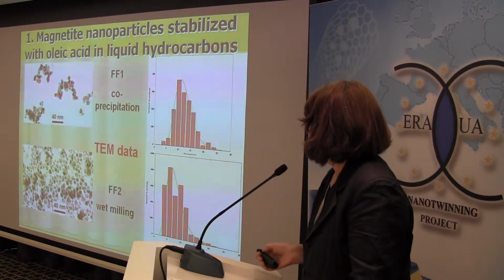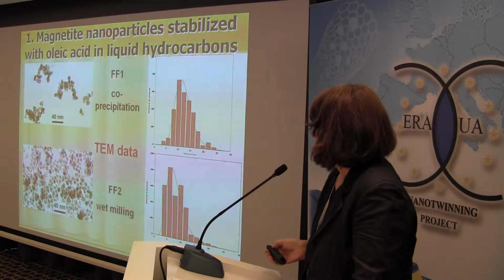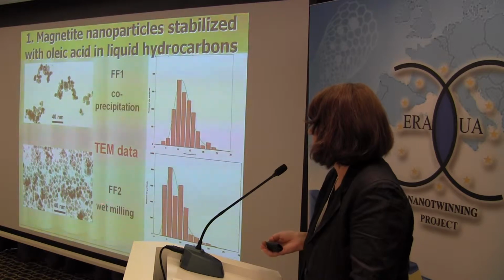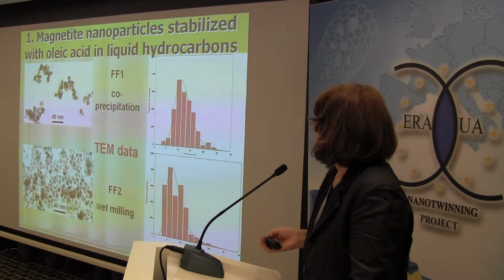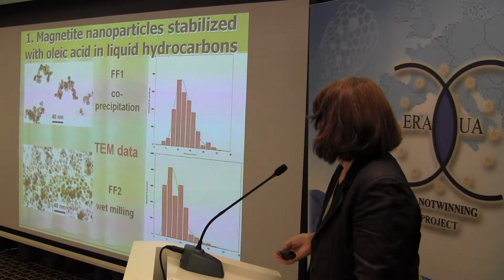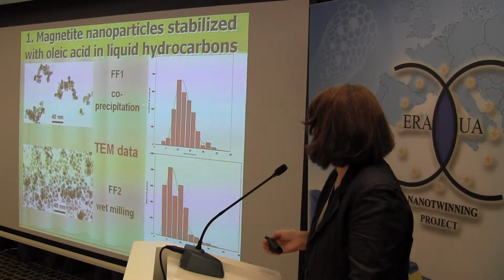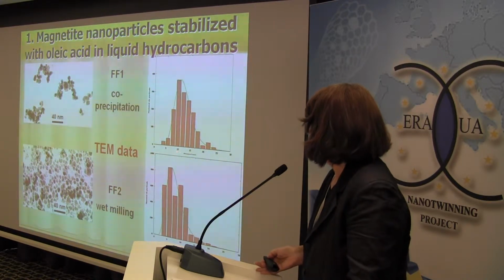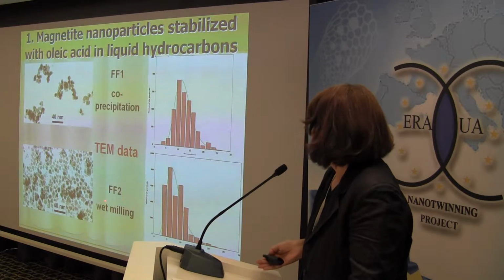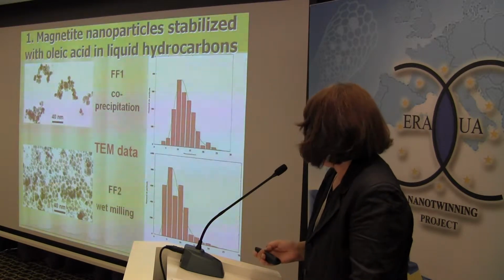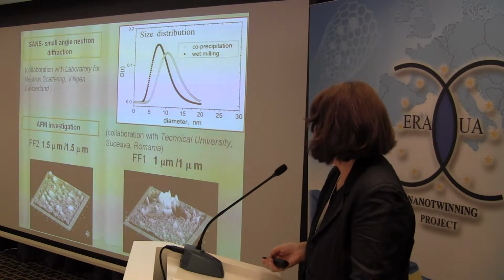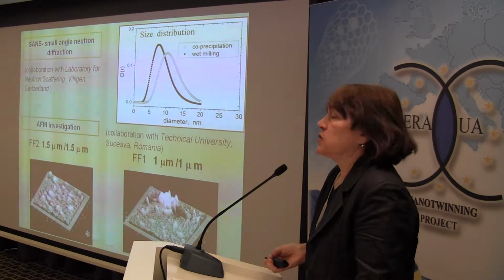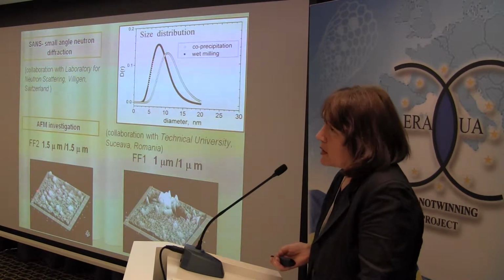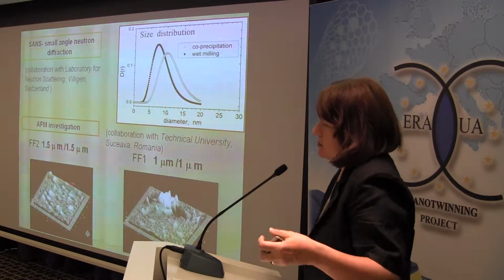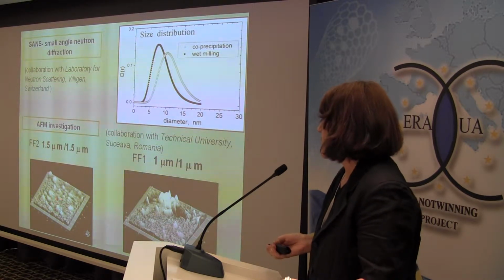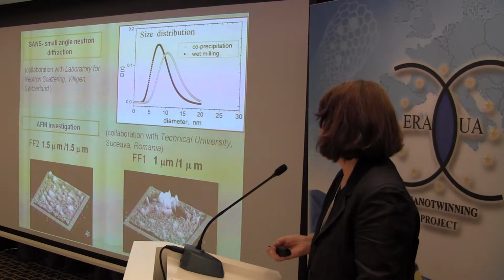Here are some results. First results, comparison between the samples prepared by coprecipitation methods and those prepared by wet milling. Transmission electron microscopy showed rather convenient distribution curves with the diameter of highest frequency appearance smaller than 10 for the first method, smaller than 8 for the second method, with quasi-round particles and even quasi-round large aggregates, as shown by the atomic force investigation, with lower accuracy from the point of view of the smaller diameters visualization, but with the advantage to let us see the topology of the particles.